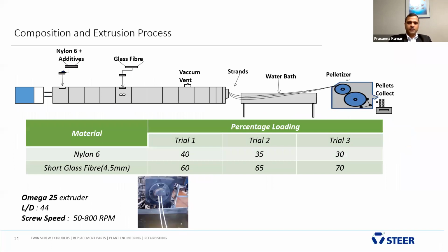This is how the setup was done. Nylon 6 plus additive was fed from the intake zone, and glass fiber was fed through the side feed zone. And as I said, we did two trials. One is with 40% nylon and the short glass fiber was 60%. Actually, three trials, 35 and 65, 30 and 70. As I said, the extruder used was a lab scale Omega 25, L by D of the extruder was 44, and the screw RPM was 800.